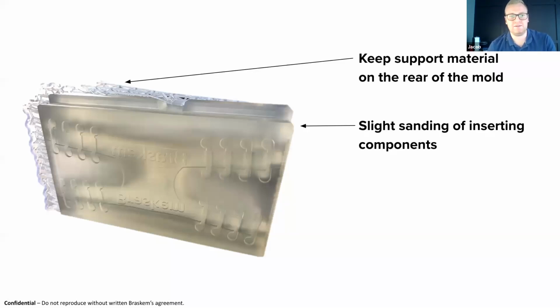One, we wanted to avoid marring the cavity surface with support materials. And so our recommendation is, if you have to orient your part and it has to have support material, orient it so that your supports are on the backside of the mold and you're not going to have any artifacts on the cavity surface. For our mold, since we were producing such a large geometry, we actually had to tilt it to be able to fit into the Form 3 printer. So we're really at the limit here of the size of parts we can make.